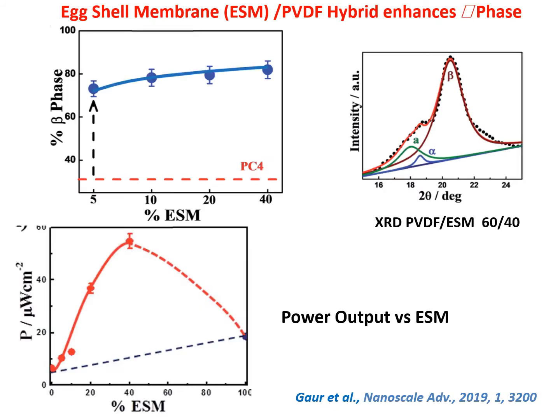Another one was very surprisingly using some eggshell. So they boiled the eggs and took the shell, crushed it, and made a mixture with montmorillonite and PVDF. And as you can see, according to the content of eggshell membrane, they could increase slightly the presence of beta phase up to 80%, which is not so bad. So this was very well identified by X-ray diffraction, and also the power output versus the content of eggshell could reach rather high power at 40% of eggshell. So this was published by an Indian group 2 years ago.